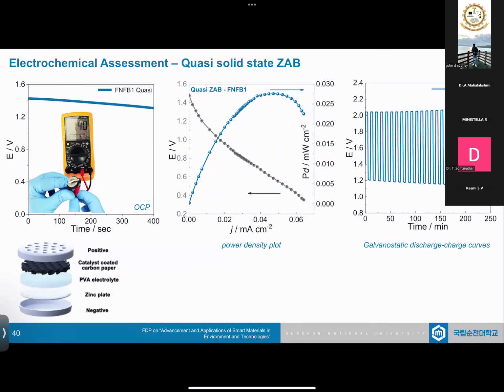So again, as I stated, we still didn't stop there. We went on to evaluate a zinc-air battery cell, a quasi-solid cell. We made a PVA gel out of the electrolyte and the PVA, and we made small battery-like cells, and we tested them. Again, the output is not that great, but still it was able to work in such nature also, proving that fluorine is enabling this material to be developed into a trifunctional catalyst.